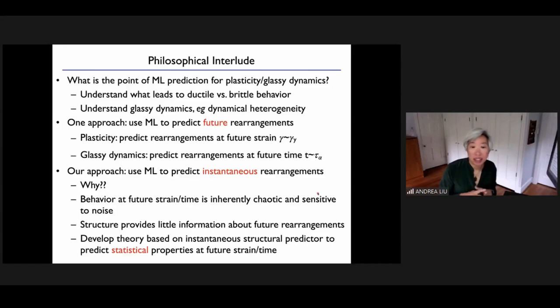And the reason why we want to do that is because if we're looking at behavior a yield strain or a relaxation time later, what happens between now and this time in the future is inherently chaotic. And so it depends on all kinds of forms of noise, including in our case, numerical noise for the athermal quasi-static shear. And it's been shown that structure actually tells you very little about what happens then. So our idea is to instead use this instantaneous structural predictor in order to predict statistical properties of the system at this future time. So we're not trying to project where the next rearrangement is or what's happening exactly in the future. We're trying to just understand statistically what would happen.